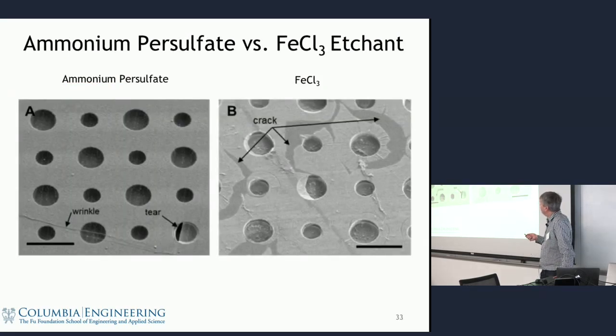So the standard etchant, when you made CVD graphene on copper, was ferric chloride, a printed circuit board etch. And when we made samples with ferric chloride, they ended up looking like this. They looked pretty horrible. But when we used a different copper etchant, ammonium persulfate, we got much better results. So it seemed that the ferric chloride actually was attacking the grain boundaries in this graphene and weakening it. So that was a crucial thing.